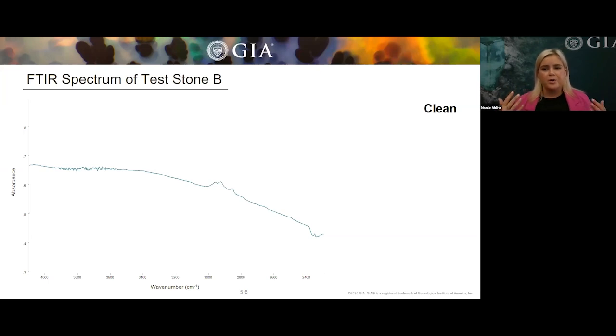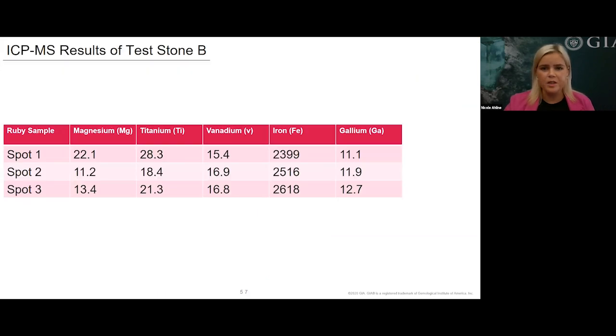So this corundum, this ruby, did get sent for an IR, again to assist with more information for that heated call, but this IR ended up just being clean. The only thing that's featured are the 3 little peaks right here, and that's just oil. So this IR was not useful for our determination of heat or no heat of this stone, but we do have those inclusions, which are basically a slam dunk for heat treatment. It isn't for origin.